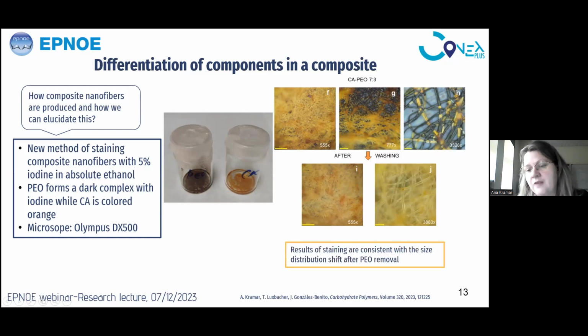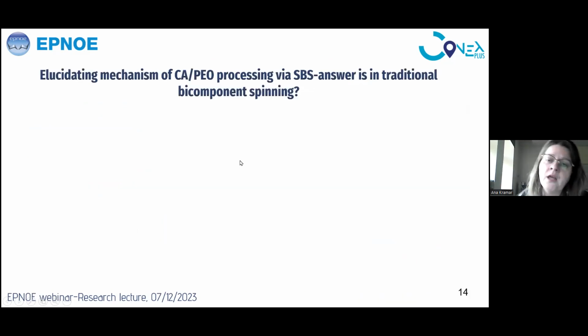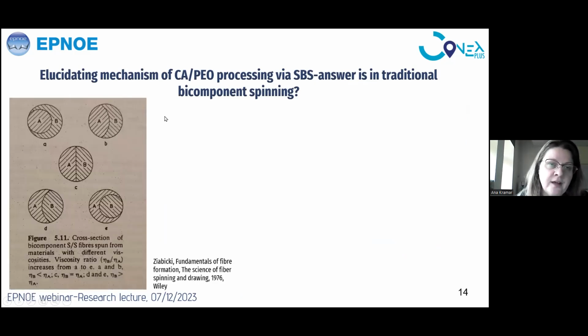And these staining results are consistent with the size distribution shift after PEO removal, because as you can see here, there are actually 2-3 nanofibers which are orange colored, that are enveloped by this dark coloration, which presumably comes from polyethylene oxide. So we were wondering if the mechanism of processing cellulose acetate and polyethylene oxide lies maybe in traditional bicomponent spinning. And here is a figure from Fundamentals of Fiber Formation, an old book regarding the science of fiber spinning and drawing by Ziabicki.